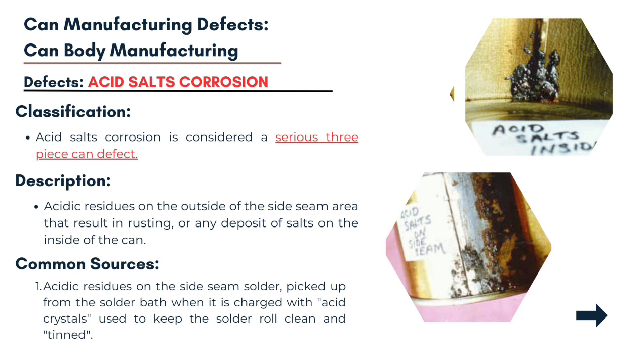This issue arises from acidic residues that remain on the outside of the side seam area of the can. These residues initiate a process of rusting, compromising the structural integrity of the seam. Furthermore, a deposit of salts can also form on the inside of the can, indicating a broader contamination issue. The primary source of this corrosion is traced back to the solder bath used during the side seam welding process.